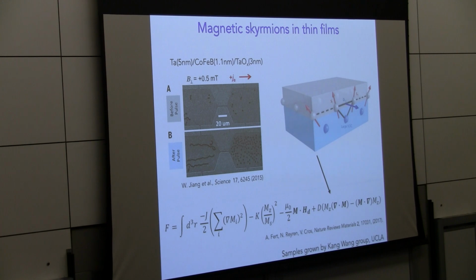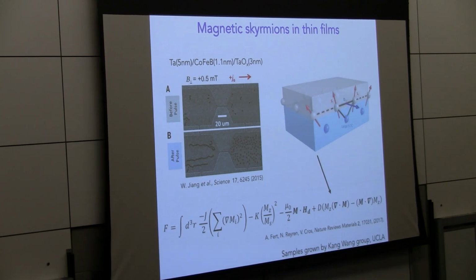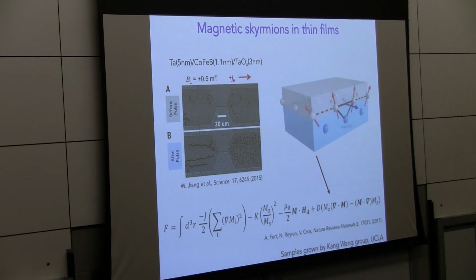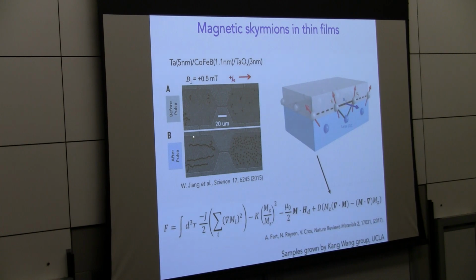So, exchange interactions can favor a ferromagnetic or antiferromagnetic alignment, and the Dzyaloshinskii-Moriya interaction will favor this antisymmetric alignment. That inversion symmetry breaking can be engineered at the interface, which is what these guys are really good at engineering. And so they grew this sample on their own. They were able to take MOKE, magneto-optical Kerr effect, microscope images. And what they're doing here is effectively generating skyrmions. They call it blowing skyrmion bubbles, but they generate skyrmions, and they can image these skyrmions.